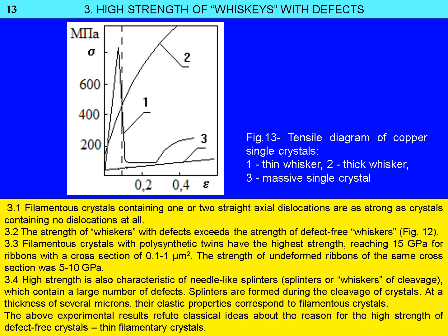Another important experimental observation is the high strength of whiskers with defects, often greater than that of defect-free crystals. As mentioned earlier, the strength of an ideal whisker is due to its surface layer, while the interior does not carry load. However, during plastic deformation, atoms move to positions of lower potential energy, leading to hardening. If a thick whisker is carefully deformed, its strength should significantly increase. This hypothesis has been confirmed.